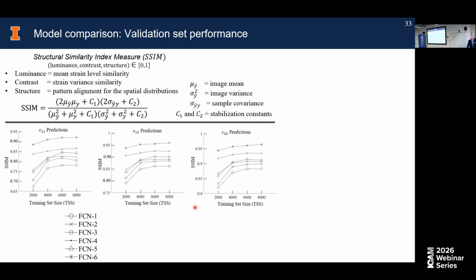So these are the 6 networks that I mentioned before. We can just look at essentially the first and the last. This is the original, just the regular CNN here. And you can see these are the 8,000 training samples. It saturates at some point fairly quickly. And it's not bad, this is at 0.85. But the complete network with all of these elements together is actually much, much better, and it produces much better results, even for smaller training sets.